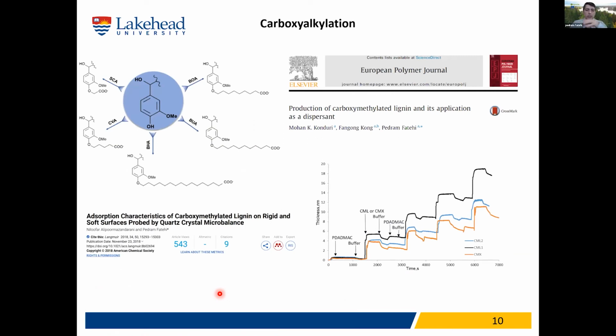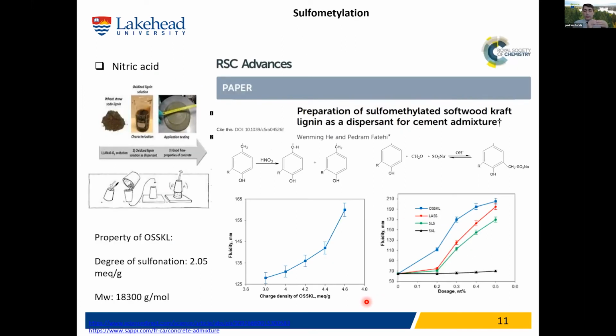So we moved to grafting. Here we tried many different grafting routes. So basically with different carboxyalkylation, for example, from 1 carbon to all the way to 15 carbon, because we wanted to see how this carbon chain affects the properties. And we noticed a big difference in terms of adsorption when we studied the adsorption of the same material. So we had the same material, but with different charge density. We noticed that the thickness of this material that is adsorbed on the surface, on our model surface, is different. So the charge density and the alkyl chain will play a big role in the thickness of the lignin that's adsorbed on the surface. And that will impact the dispersion properties significantly, because it makes a coating layer on the particle, and with different mechanisms, it can disperse particles in the solution. I will get back to the mechanism later on.